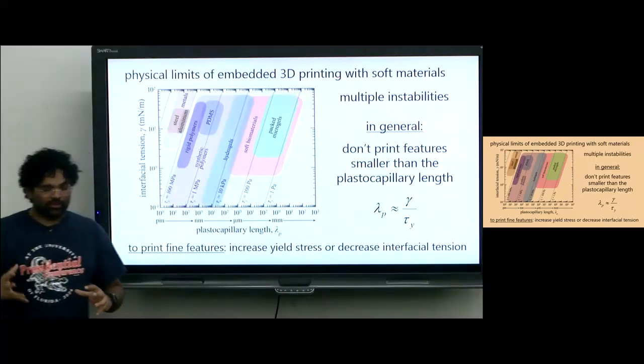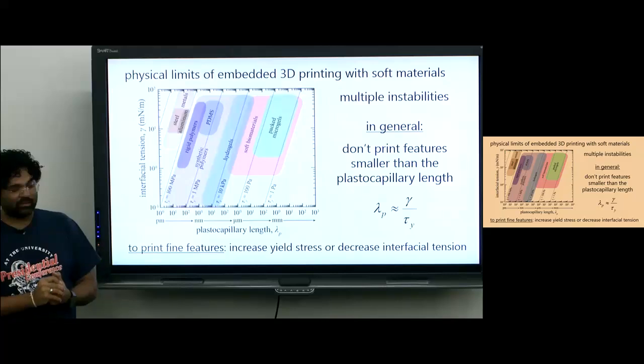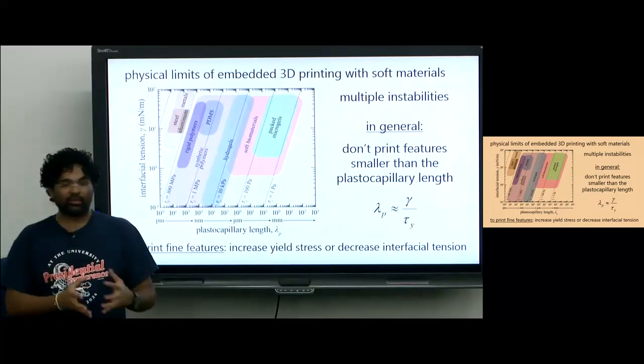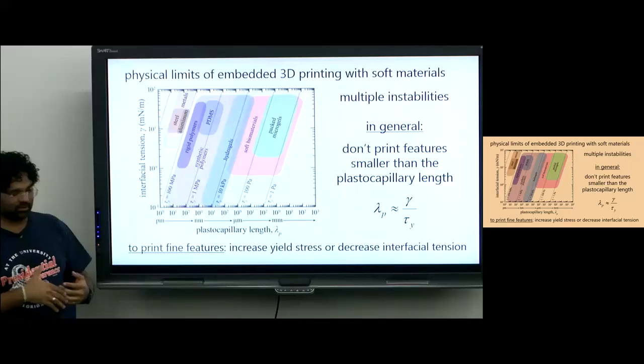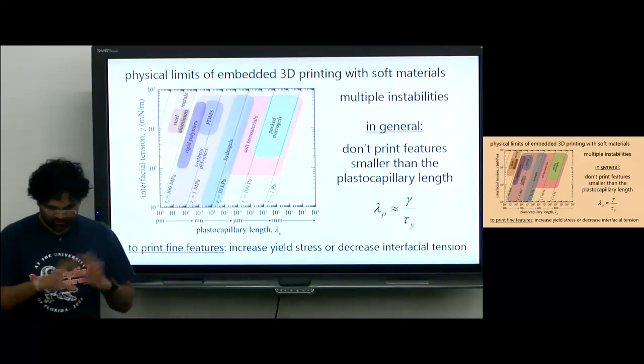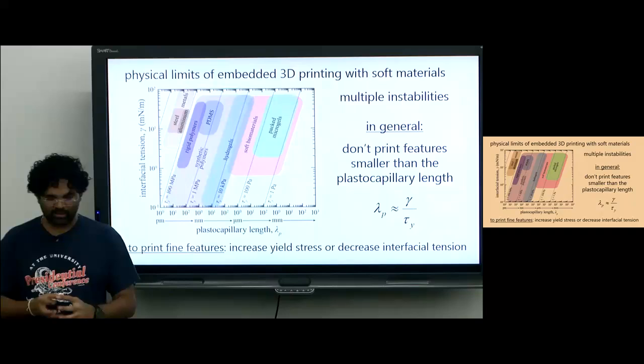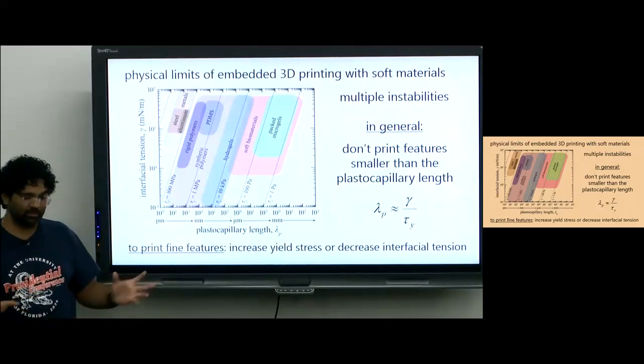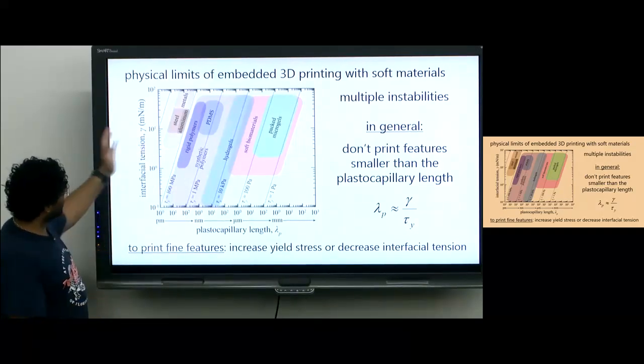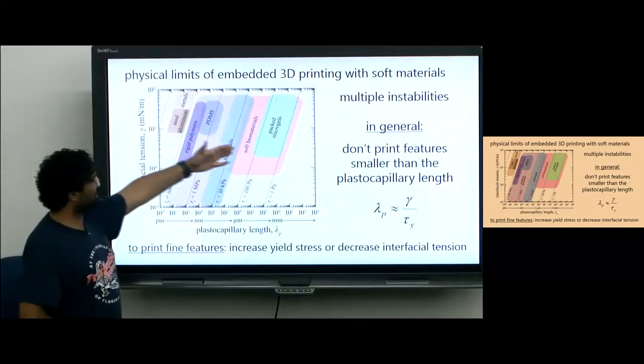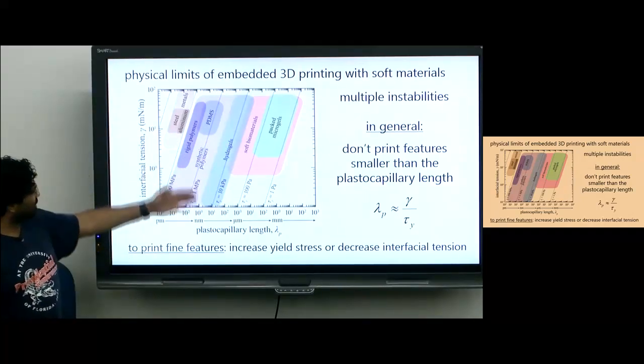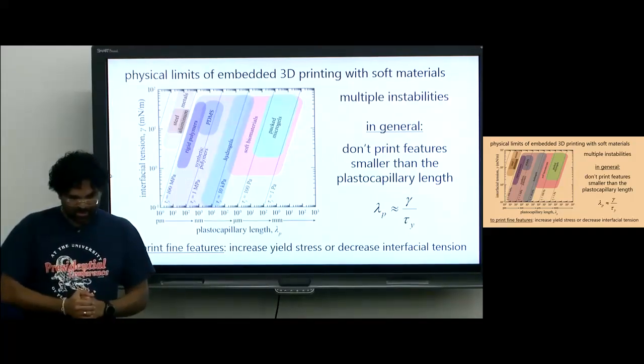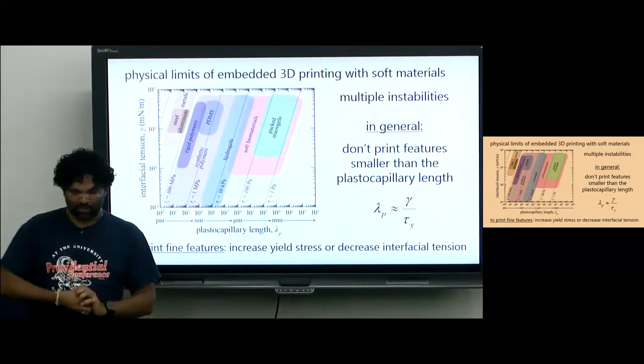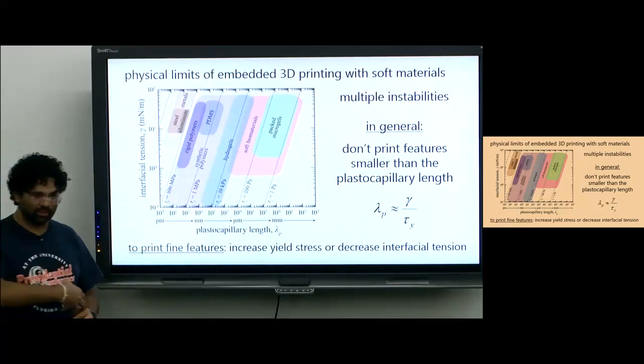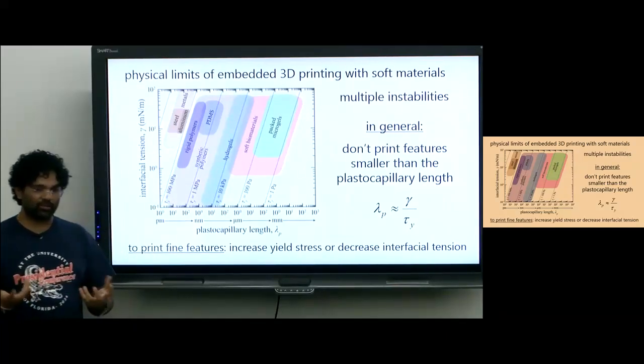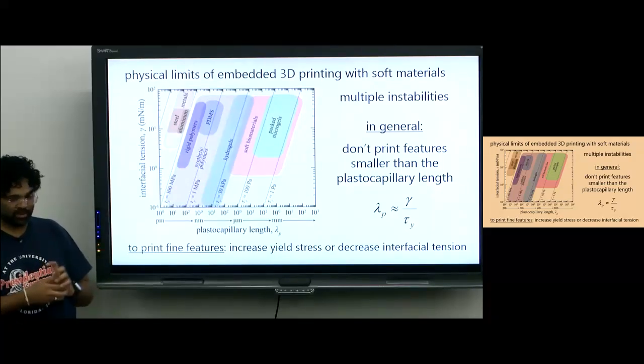Another limitation when we do this sort of soft material 3D printing is the plastocapillary length, which is essentially a ratio of surface tension to your yield stress. As a general rule, the idea is to not print any features that are smaller than the plastocapillary length for any material. In this graph, you can see a whole range of materials, from metals and polymers all the way down to soft materials like microgels and hydrogels. So, in order to print fine structures, we can either increase yield stress or decrease interfacial tension. We choose the second approach, where we try to decrease interfacial tension and then print stable structures.